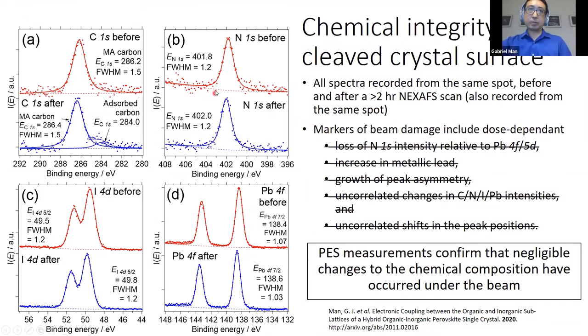This is a collection of core level spectra where the red spectra were recorded from the same spot, and then a NEXAFS scan was performed. That took over 2 hours. And the blue spectra were all recorded from the same spot after the NEXAFS scan was done. The typical markers of beam damage for this class of material include dose-dependent loss of nitrogen 1s intensity relative to lead. We don't see that. There could be an increase in metallic lead. We don't see that at lower binding energy over here. There could be a growth of peak asymmetry, uncorrelated changes in the intensities, and/or uncorrelated shifts in the peak positions. We don't see any of that. So we have some confidence that the material is chemically intact under the beam for hours.